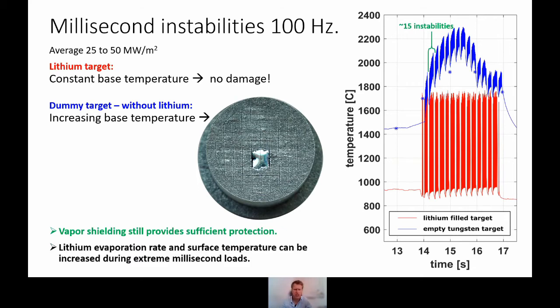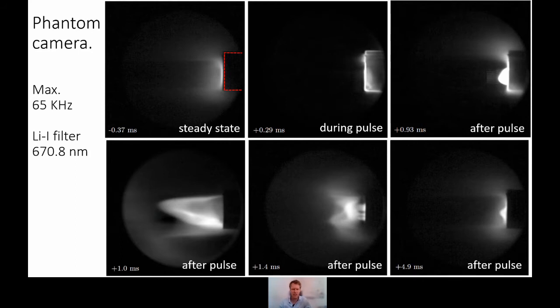Yet the target survives. But again, we should note, evaporation may be significantly increased in these cases, right? Because to deal with these extremely high loads, we will get increased temperature, despite the temperature locking effect, to evaporate enough lithium. And in fact, now I'll show you some of these camera images. We can have fantastic measurements, really beautiful images, I think, of what happens during a pulse. So you can see